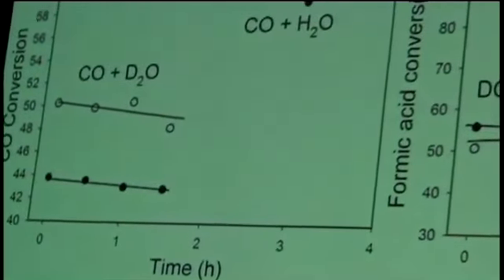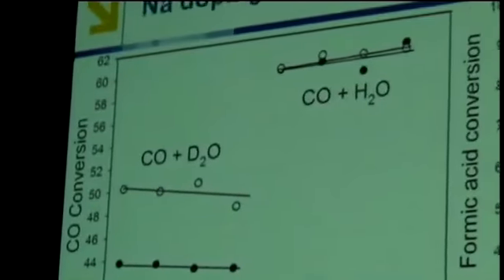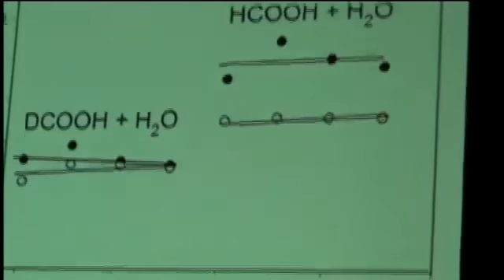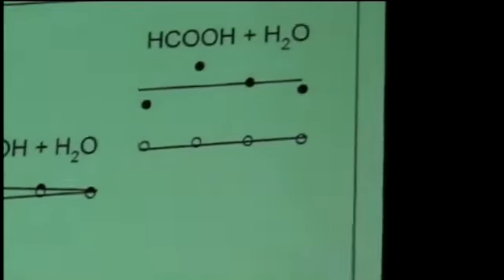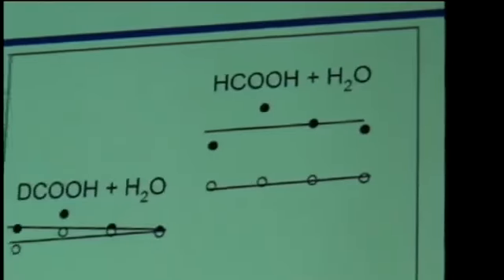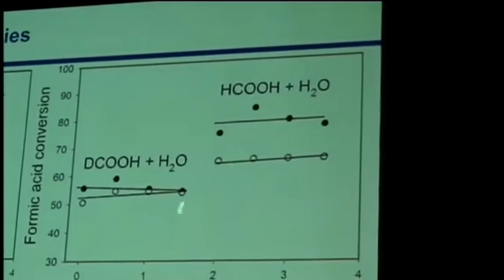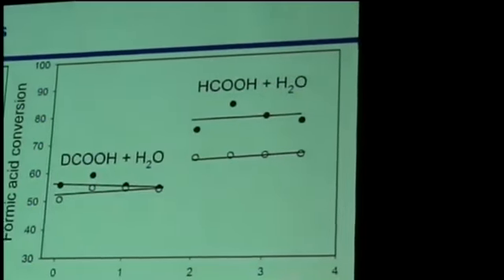And to probe that more, we also looked at steam-assisted formic acid decomposition, which should also pass through formates. And this is the undoped here. The kinetic isotope effect is 1.4, just like in water gas shift. And when we added the sodium, there was also a decrease in the kinetic isotope effect from 1.4 to 1.2. So certainly it's in favor of formate mechanism.